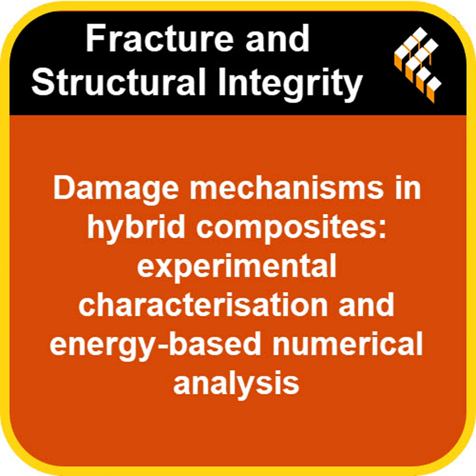Okay, so the models seem reliable. What key insights did they get about how the damage happens by looking at these simulations? What did the models reveal that the experiments couldn't? This is where the simulations really paid off. One of the most important findings was that damage within the individual layers, intralaminar damage, things like the epoxy cracking and fibers breaking, was the main way the material absorbed energy and ultimately failed across all the different layering styles. So failure inside the layers themselves was dominant.